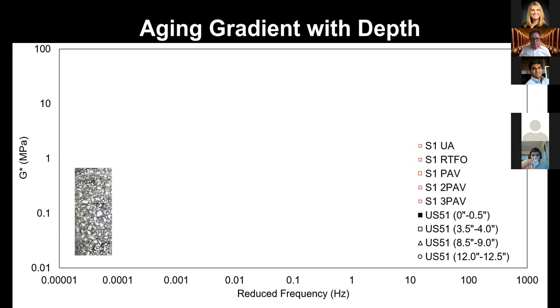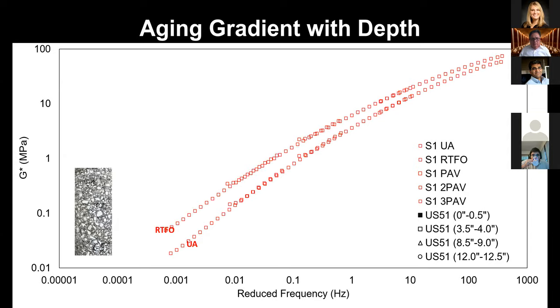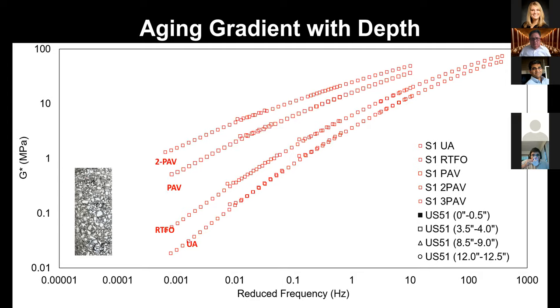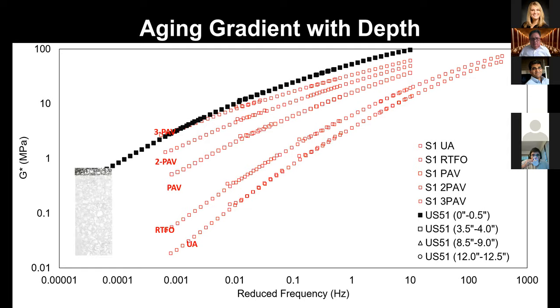The graph compares the lab aged base binder S1, a 64-22, and the values here will be shown in red. The first is the unaged, the second is the RTFO aged, PAV aged, single PAV, double PAV, and triple PAV. They then compared those samples to the asphalt extracted from the cores in the field. This is the US 51. The top inch matches very closely or exceeds the aging seen at 3 PAV in the lab.